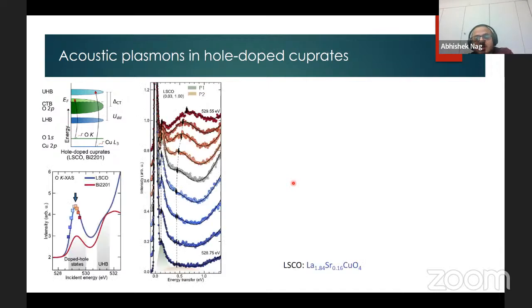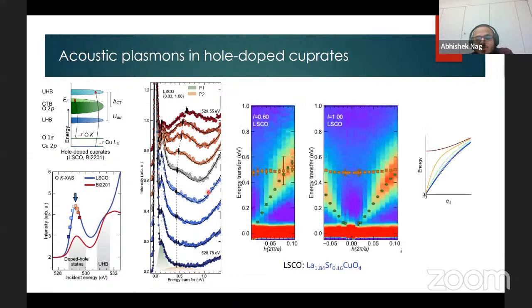So we did incident energy dependent RIXS across the hole peak of the cuprate lanthanum strontium copper oxide, LSCO. And as we can see, there is one sharp peak at around 130 milli-electron volts that has a Raman behavior and almost does not change in energy as the incident energy changes. This suggests that this peak has a coherent nature, unlike this high energy peak. So we started looking at the momentum space propagation of this sharp peak. And as you can see here, this sharp peak disperses towards zero energy, much like the acoustic plasmons.